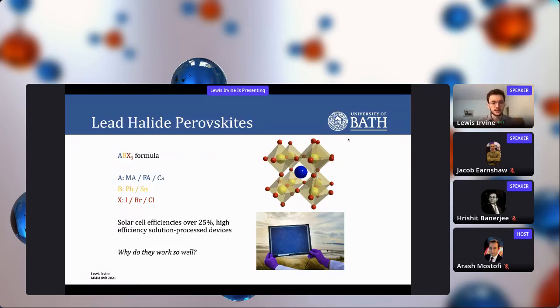In general, they take this ABX3 formula with these octahedra here. These octahedra tend to be made of halides, and inside each octahedra you have either lead or tin, and you have what's typically an organic but sometimes inorganic A-site cation as well. And so this range of options means that you can tune your halide perovskite quite a lot. And the reason everyone's interested in them is for their optoelectronic properties. So people are making really good solar cells with them, with high efficiencies, but with really cheap solution processed devices.